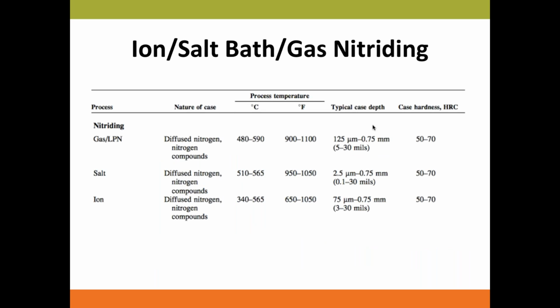And I'll quickly cover the different nitride techniques. You have ion nitride, plasma nitride, salt bath, and gas nitride. You can see their processing temperatures are a little bit different. Ion can be the lowest because plasma provides extra energy on top of the temperature, so the temperature of the sleeve can be lower. And the salt bath, because the part is put into a salt which has better heat transfer, the temperature of the sleeve itself can be lower as well. But the Rockwell they're able to achieve is almost identical. So a lot of people will say they are almost identical, and I think they will work the same.